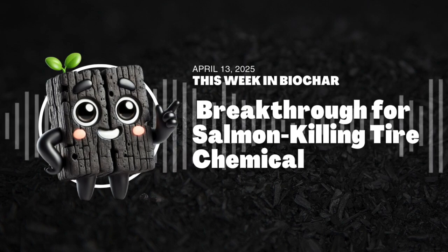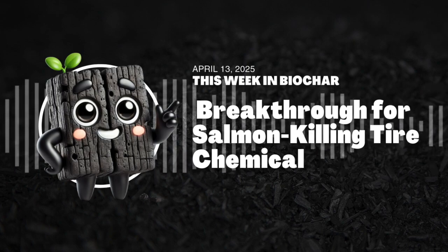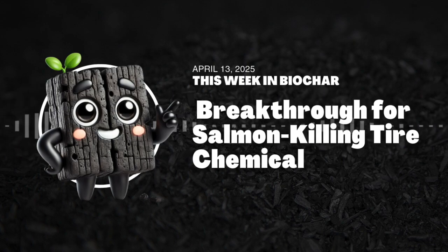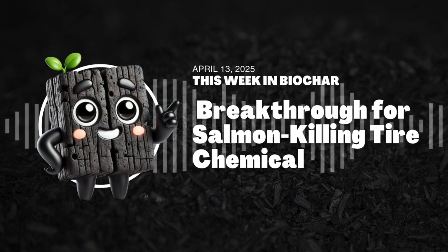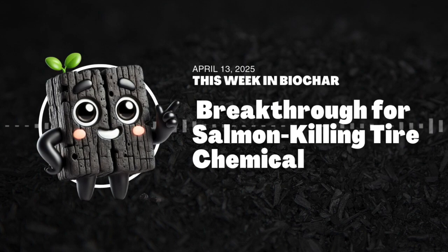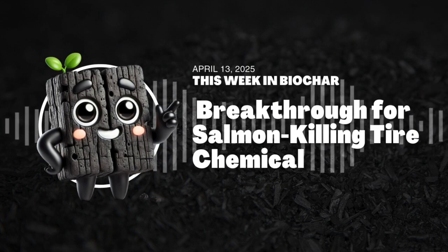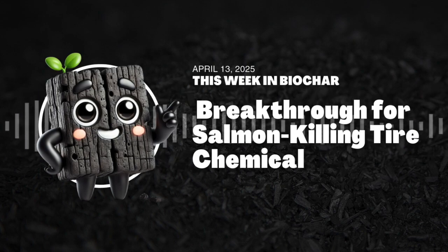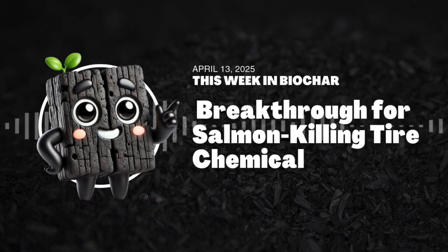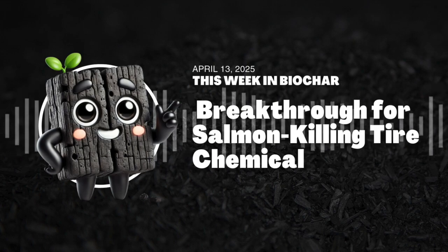Definitely. So let's jump into that first one, the work out of Nantes Université in France. They're using syngas to activate biochar. That's right. Syngas, mostly hydrogen and carbon monoxide. They've got this patented pyrolysis reactor, and the really clever bit is what they call in situ partial reduction. Okay, in situ. So happening right there. Exactly. They've added this zone down at the bottom of the reactor. Freshly made, really hot biochar meets hot syngas coming from another part of the same system. So it's like an immediate upgrade step built right in. And the goal is boosting the surface area.